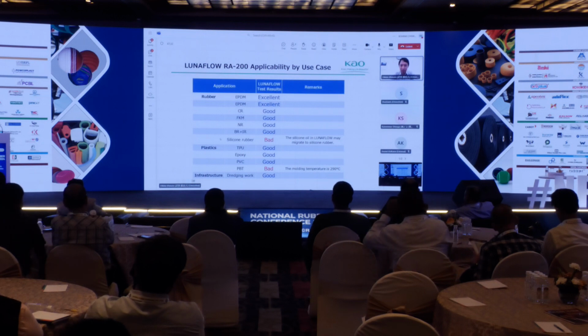Here is the result. This may also be our LunaFlow application use case. This is feedback from our Japanese customer. As for rubber, for example, EPDM and fluoropolymer, CR rubber, FKM, and NR, BR and IR have very good release performance using LunaFlow. However, silicone rubber is not good. This is because the silicone oil in the flow may migrate into silicone rubber, so silicone is not compatible.